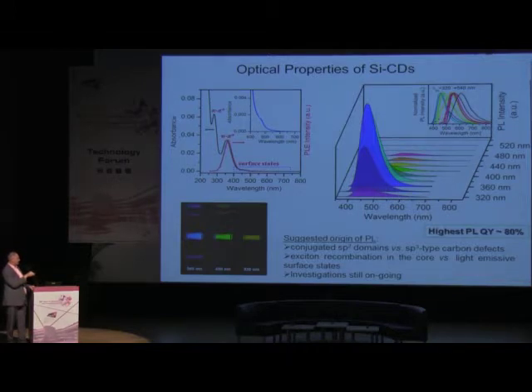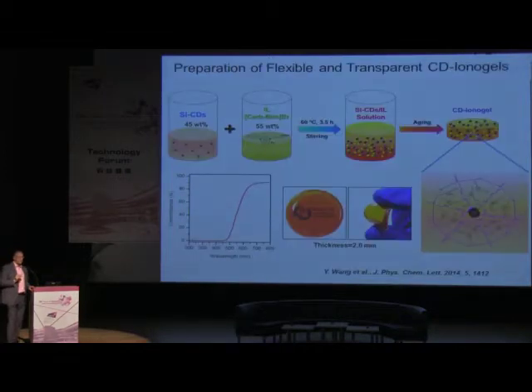So about the origin of photoluminescence here, there are still some discussions in literature. It may be related to sp2 domains or sp3 type carbon defects which are closer to the surface, while these are domains in the core of carbon dots, so the investigations here are still ongoing. But the fact that we can control the emission by excitation wavelengths, we actually realized it, and I will show you on my next slide how we did it.